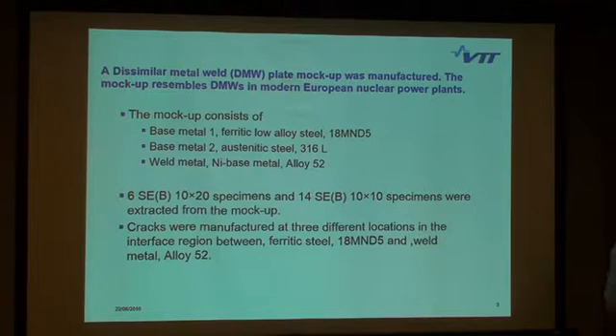What we did in the experiments was 14 experiments with 10 times 10 single-edge bend specimens and 6 specimens with the 10 times 20 size. The cracks were manufactured in the interface region of the ferritic steel and the weld metal, because it's the location with the lowest resistance.